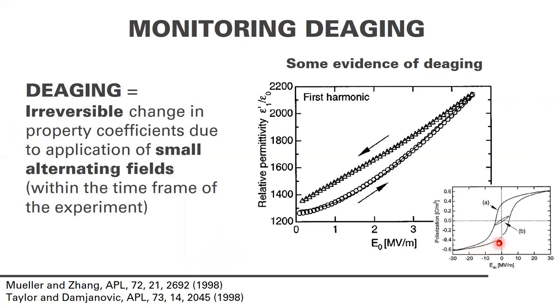The macroscopic hysteresis loop of a thin film is shown here. And what they've done is they've applied electric fields at weak electric field amplitudes to study permittivity effects. And so if you start your measurement here and increase your amplitude of electric field, you go up the bottom line. And then as you come back down, you come down a different line. So you have a different domain state, okay? And that's evidence of de-aging.